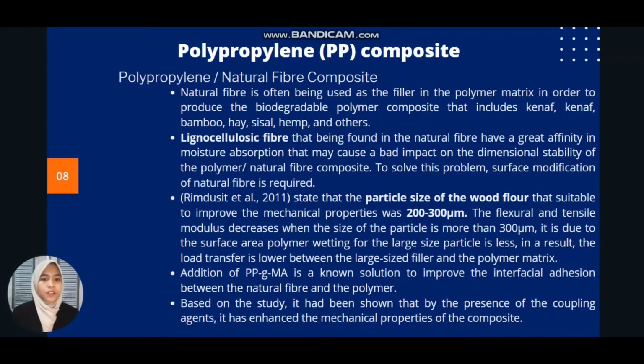So for the PP natural fiber composite, the natural fiber is often being used as the filler in the polymer matrix in order to produce the biodegradable polymer composite. So in this case, we use kenaf, bamboo, hay, sisal, hemp, and rice. And then lignocellulosic fiber that is found in the natural fiber has a great affinity for moisture absorption that may cause a bad impact on the dimensional stability of the polymer natural fiber composite. So to solve this problem, modification of natural fiber is required.